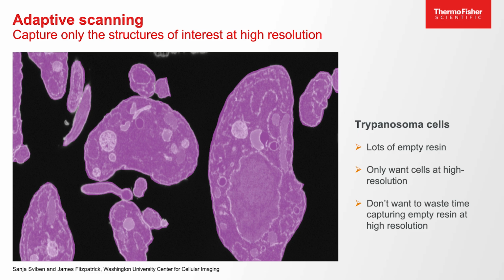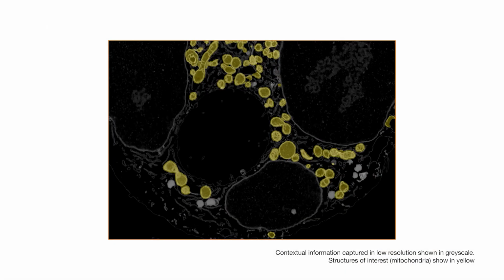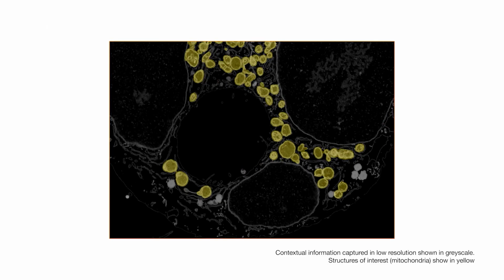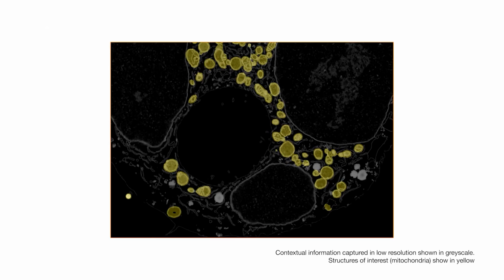Sometimes you have cells or organisms which are surrounded by just the resin that they're embedded in. And this resin does not contain any information, but in the conventional way of scanning, you still scan with the selected high resolution. So by using artificial intelligence, you create a map or a mask of your region of interest, and you kind of teach the system to recognize the region of interest against regions that are less important or do not contain information. So at the end of your acquisition, you have a volume that has the contextual, low-resolution information and traces your features of interest at the desired high resolution, which saves a significant amount of time.